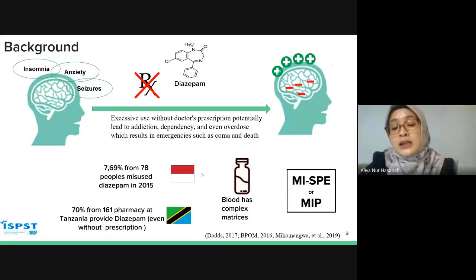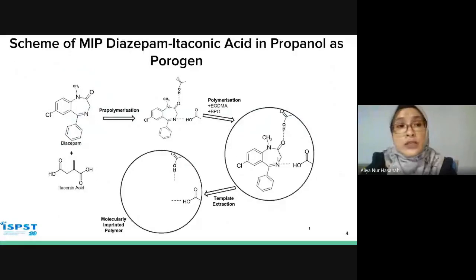And this can be overcome using a novel sample preparation method, which is molecular imprinted solid phase extraction. So in this research, we will synthesize molecular imprinted solid phase extraction for diazepam extraction in blood samples, using itaconic acid as functional monomer and propanol as a porogen. This is the scheme for the synthesis of diazepam and itaconic acid in propanol as porogen.